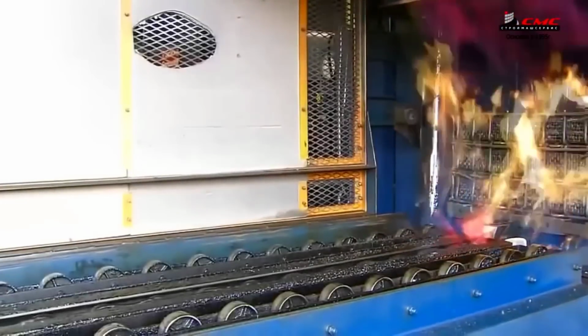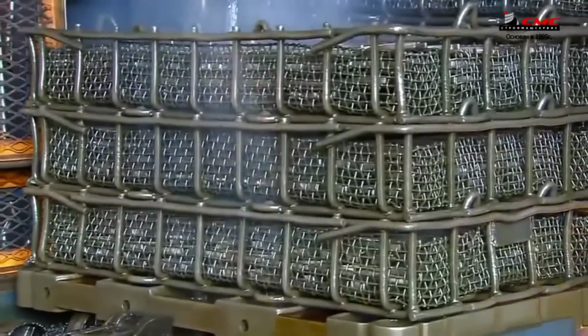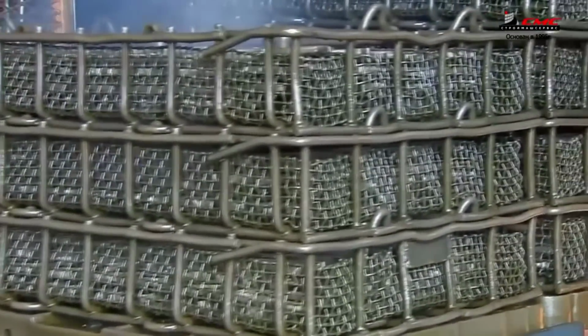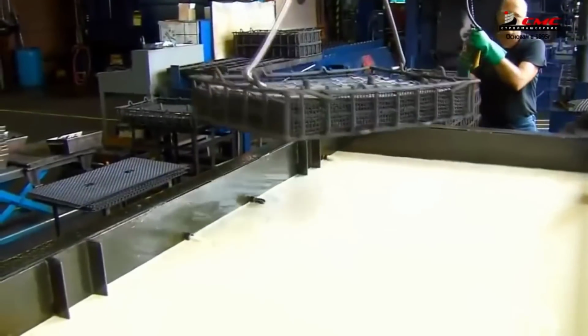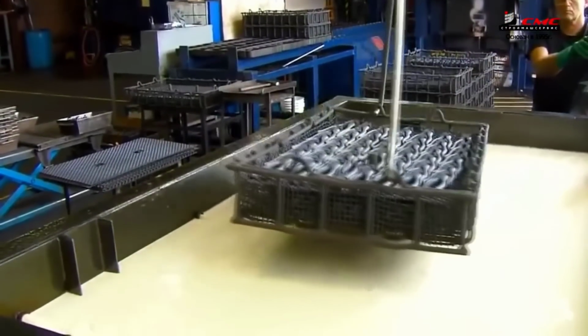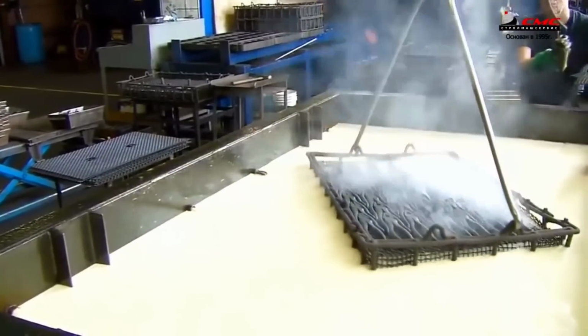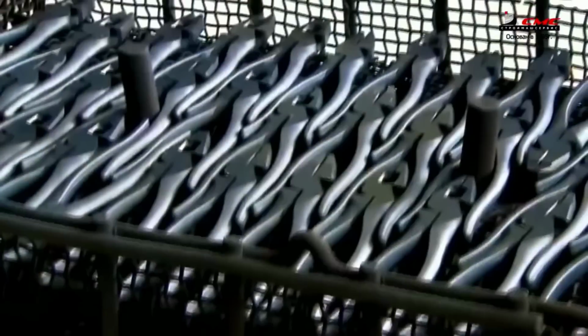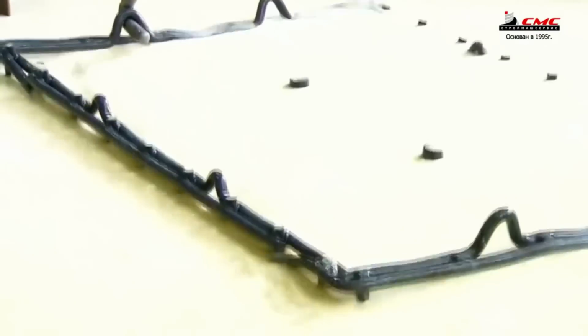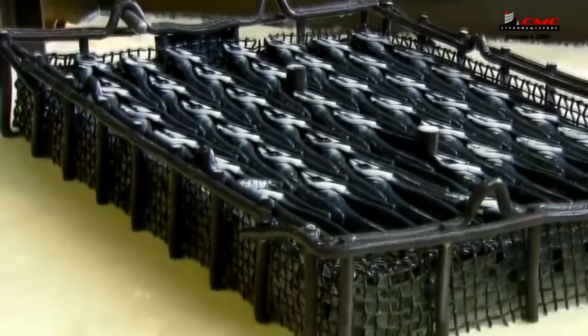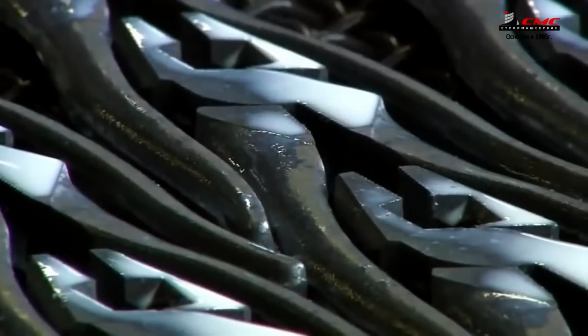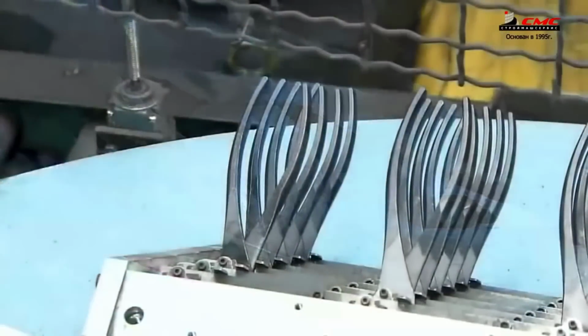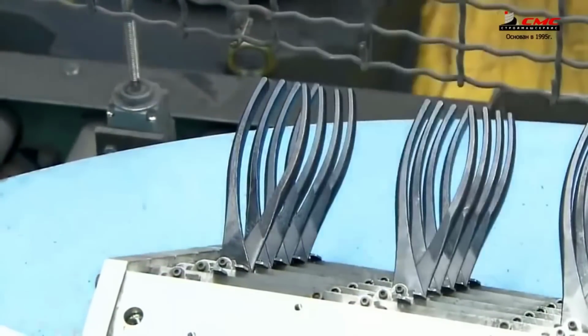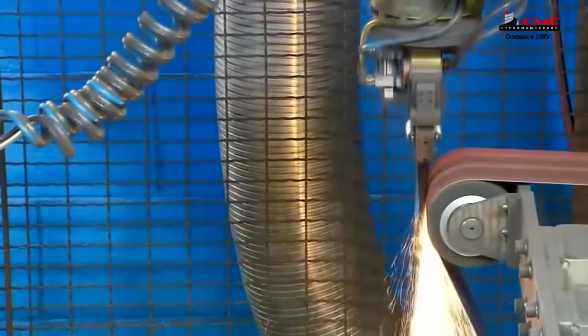Subsequently, these pliers are sent to a gas furnace for another 2-hour heat treatment, a crucial part of the tempering process. After removal from the furnace, they are immersed in an oil solution, a departure from the rapid cooling in salty water employed for regular pliers. Steel is an exquisite material, making meticulous heat treatment essential to avoid compromising its quality.